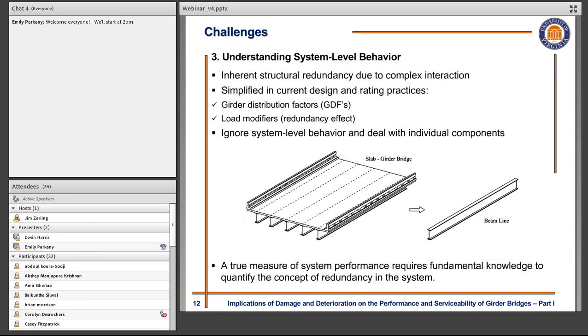As we start looking at bridge structures, the thing that makes bridge structures a little bit different from our classical frame type analysis is the system behavior. And this is actually a very important one because when we look at design, we tend to treat things or design things on an element level basis. And as a result of this system behavior, there's a great deal of inherent structural redundancy due to the complex interaction of the components. Typically, as I said, it's simplified in design, but it's also simplified in the rating, which is the evaluation side of the in-service structures. Things like girder distribution factors, load modifiers, and a true measure of our system performance requires ultimately a fundamental knowledge of the concept of redundancy in the system.